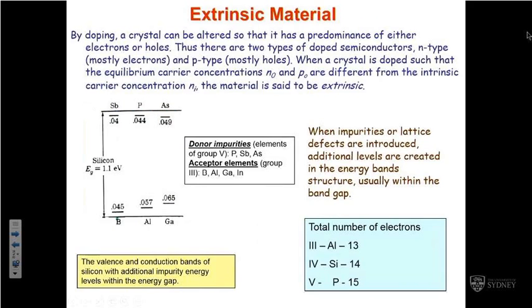Okay, this just shows some actual values from some research that has been done. What have we got here? So here you can see this is silicon, which has a band gap of 1.1. This is your valence band down here. This is your conduction band up here. Acceptors have been introduced into your system, for example, aluminium that we have talked about. And you can see that the aluminium has given rise to an energy state 0.057 eV just above the valence band maximum. And so that's really close.